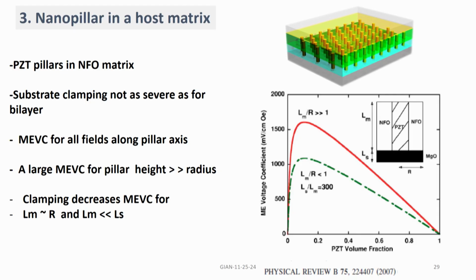This is for a nano pillar in a host matrix. These are pillars of PZT in a host of nickel ferrite, and the nano pillar is on a substrate. Once again, there are parameters corresponding to the substrate: here is the radius of this substrate, and then L sub m is the height of this nano pillar. Ls is the thickness of the substrate, and we assume magnesium oxide.